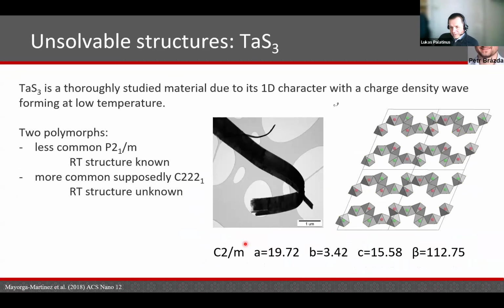The first example is one that I like a lot. It's a very simple structure. It's tantalum trisulfide, and it's been thoroughly studied for decades. There are hundreds of papers on TaS3, and yet its crystal structure has not been known, because it forms, as you can see in this picture, these very plastic, exfoliated, bending small crystals, which were impossible to grow in large enough size and good enough quality for single crystal X-ray diffraction, and it was not possible to solve the structure from powder diffraction either.